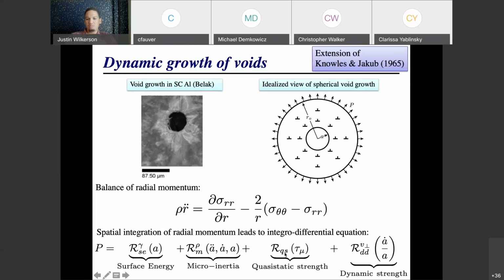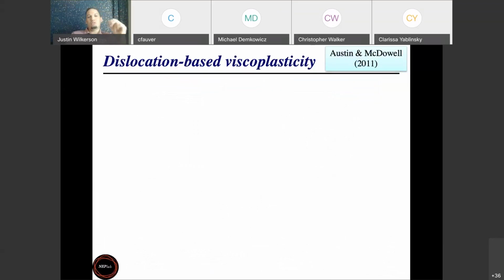Okay, and so we split that term into 2 components, one associated with the quasi-static strength of the material. So what kind of far field pressure do you have to apply just to get the dislocations to start moving? And then a dynamic strength term, which accounts for the fact that I'm going to drive these dislocations at very high velocities, so there's going to be an overstress that's needed to propagate them at a high rate. And that's essentially the rate sensitivity of the matrix material. So for those last 2 terms, I need to choose a plasticity model that's appropriate for the matrix material deforming at these incredibly high strain rates.